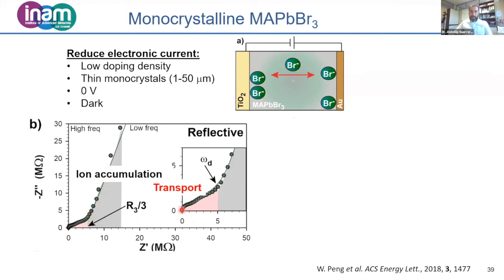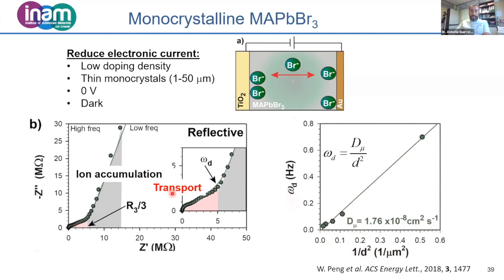So this red path that we observe here, this is the 45-degree angle observed previously in the sensitized solar cells. And this vertical line is the accumulation of ions that typically happens at low frequencies. Okay. So from this data, and making a batch of different thicknesses for the monocrystals, it is possible to calculate the diffusion coefficient of the ions inside the perovskite material. And in this case, it was giving values of 10 to the minus 8 square centimeters per second.